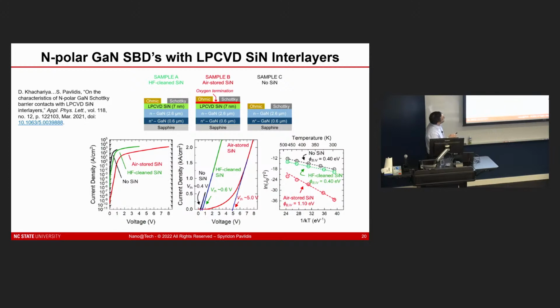In this case, we also looked at different surface treatments to that silicon nitride prior to Schottky metal deposition. One case where we dipped the samples in HF to remove oxides that were forming at the surface, and another one where we let the oxide grow after letting the sample sit out for a few days, and then put the Schottky contact down. And you can see that this has a very important implication on the device's performance. This curve here, the red one, is the sample with the oxygen-terminated surface with a large turn-on voltage. But if you use HF to treat the silicon nitride before putting down your Schottky contact, the turn-on of that HF clean surface is slightly higher than your bare or control device, but you still get high ideality factors, and the silicon nitride is just a thin inner layer there as well.